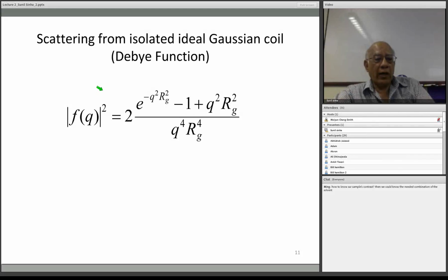If you want to do it with a concentrated solution, on the other hand, you can selectively deuterate some of the chains, and they have a contrast, and they're sufficiently dilute that they give you a form factor which stands out above. So you can have, for instance, a polymer melt, where the space is full of polymer chains, but if a few chains are deuterated and the rest are not, or all the chains are deuterated and two or three are protonated, you can get the form factor of the chains in the melt from this method.